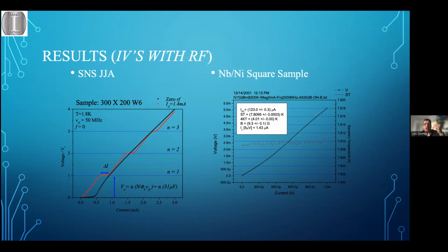Actually, it's a non-equilibrium system. It's much more complicated physics and not very well understood. But what is remarkable is that as you apply the signal, you will see a response in the IV characteristics. So you can use this system as a detector for signals. But to the naked eye, by a simple IV, the nickel and niobium system doesn't show anything, not like in the nickel gold system. In the nickel gold system, whatever signal I put, if the array is perfect, I will get very, very sharp plateaus, and when I measure the voltage, they occur at very precise values.